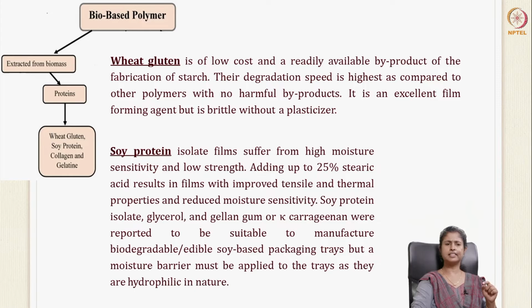It is an excellent film forming agent, but the problem is it is brittle without a plasticizer. So you require plasticizers to make it more flexible. Another biopolymer uses soy protein. Soy protein isolate films can suffer from high moisture sensitivity and low strength. That is one of the problems. They are not a very good barrier against moisture and they do not have much strength. But you can add up to 25% stearic acid, and that results in films that have better tensile and thermal properties and reduced moisture sensitivity.